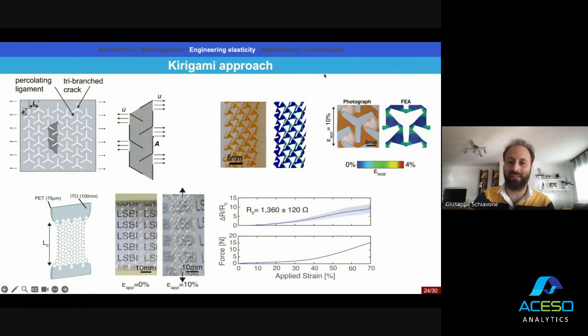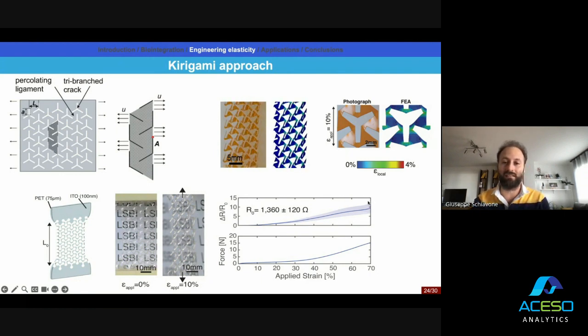So in the movie in the center there, you see one experiment where we were actually testing the durability under stretching of these materials. And in the bottom example, we applied that to films of what's called ITO, so indium tin oxide. Indium tin oxide is an interesting material for biological applications because it's a conductor, but it's also transparent, which is a rare combination. So we can have devices that have conductive traces, but still we can look through them, so we can image the tissue underneath. So we can apply this microstructuring technique to that, and we can stretch it and measure the resistance, and also do some reliability measurements. So just look at what the endurance of these devices would be.